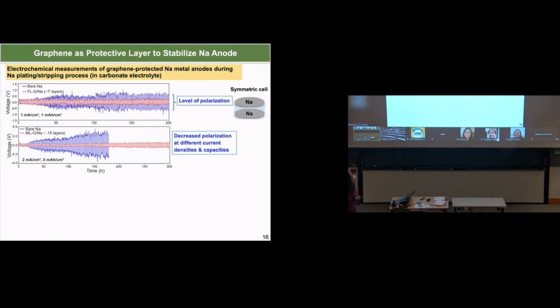Okay? So here I want to show the electrochemical performance, since you're going to see a lot of these kinds of curves in the following slides. So I want to spend a couple of minutes to explain what you are looking at here. The way we test whether the graphene film works or not, whether it can stabilize the sodium metal electrode, is we use something we call a symmetric cell. So this is a symmetric cell. We use a piece of sodium metal against another piece of sodium metal, and we put the electrolyte here, and we coat the graphene film on the sodium metal electrode. In this case, you can see that there is really no cathode material here, so there's only anode material. So we can completely eliminate the influence from the cathode, and we can also enlarge the issues for the sodium metal electrode by using this typical symmetric cell design.